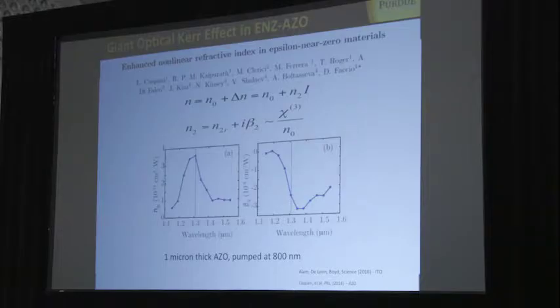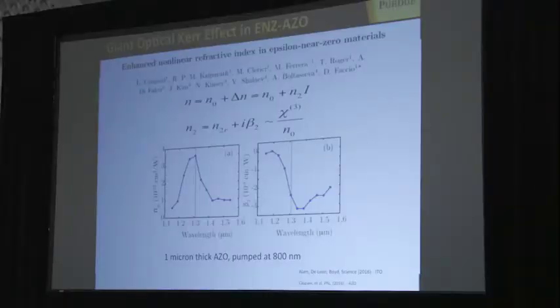What it means is, if I work close to the point where epsilon is close to zero, and if the imaginary part is small, which is true for AZO and ITO, quite small, like 0.1, not exactly zero but rather small, that means the linear refractive index is really small. So the nonlinear term could become larger than the linear one. And this is kind of unusual. The whole idea of perturbation theory for nonlinear optics should in this case be revisited.